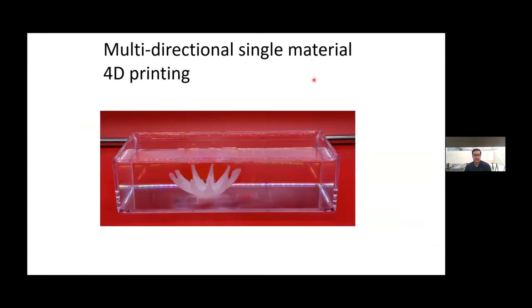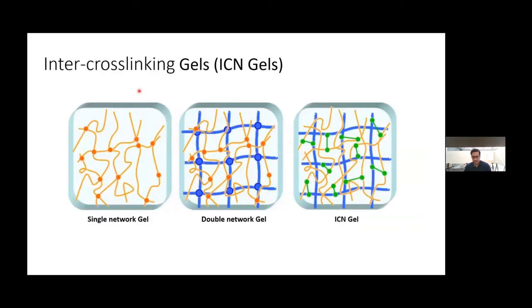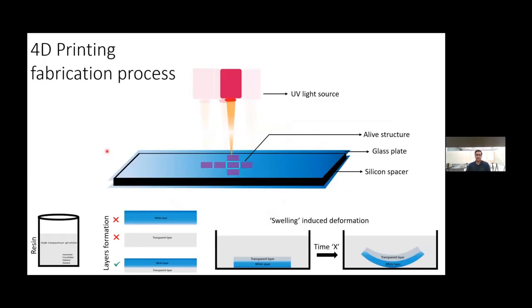In this section, I would like to talk about multi-directional single material 4D printing. For this system, I have used inter-crosslinking gel, which we call ICN gel. In this fabrication process, you can see this is the UV light source, and this is the glass plate and silicon spacer. In this process, we don't need to change the material. With a single material, we can create the bilayer system. You can see we can create a white layer and a transparent layer, and when we put this structure into the water, it transforms. The actuation happens.